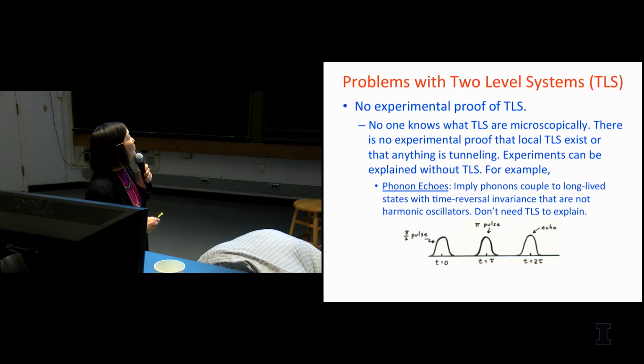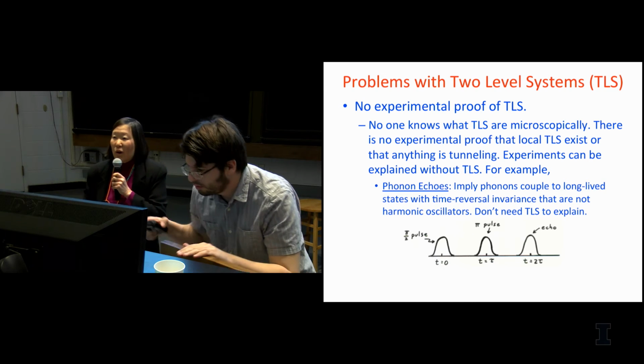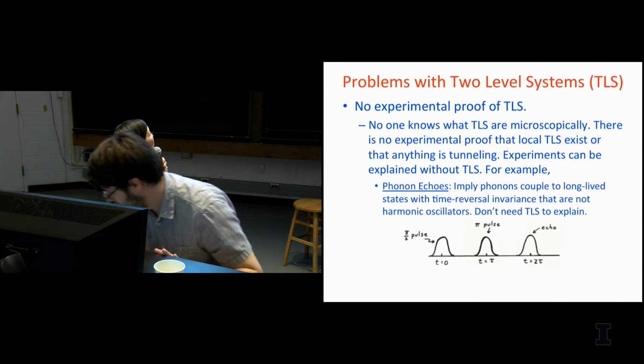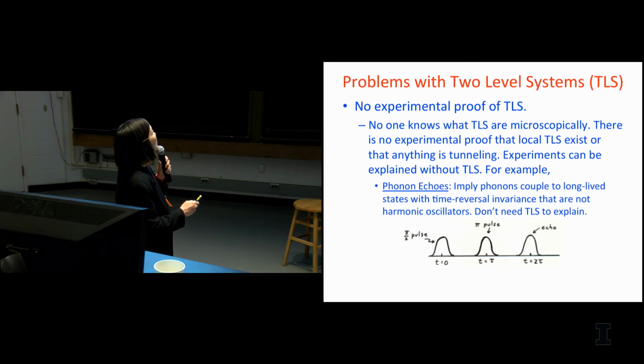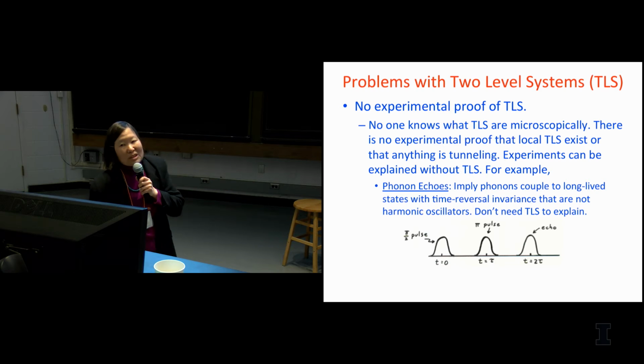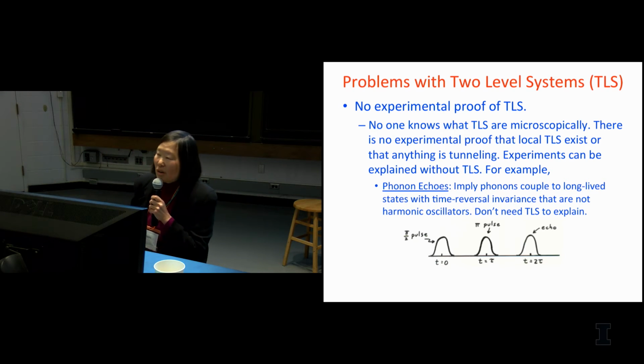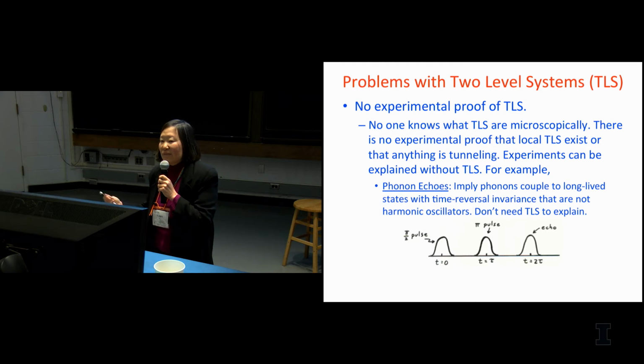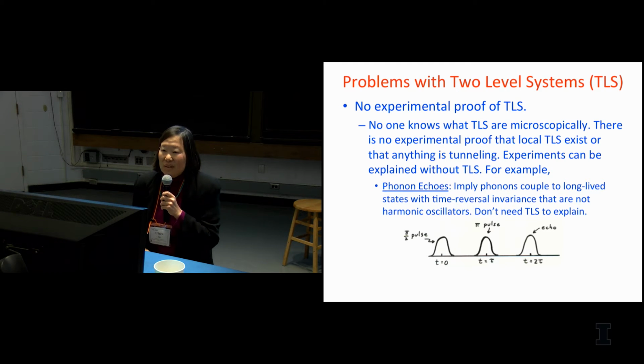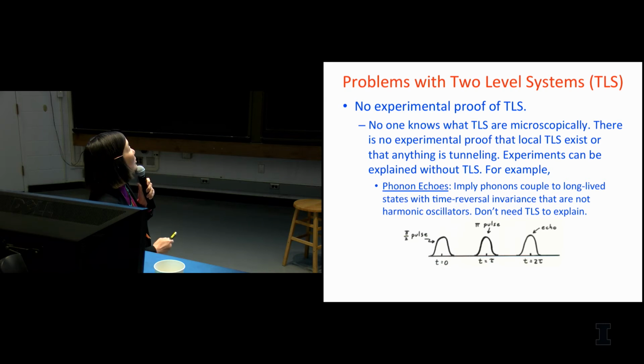Phonon echoes, for example: you put in a phonon pulse. This works just like spin echoes in NMR. Put on a phonon pulse, wait a little while, put on another pulse, and then you get an echo back. All this implies is that you've got phonons that strongly couple to long-lived states that have time reversal invariance, and they're not harmonic oscillators. You don't need two-level systems to explain that.